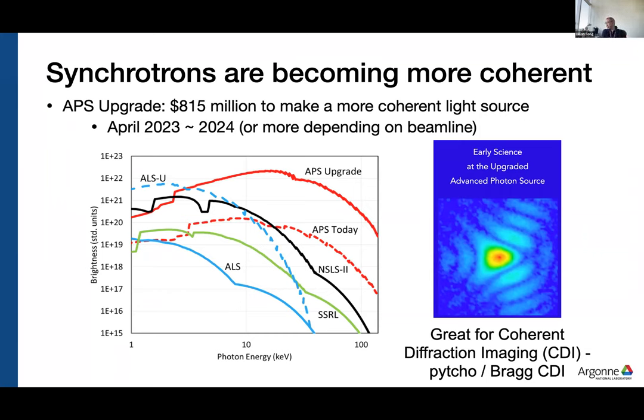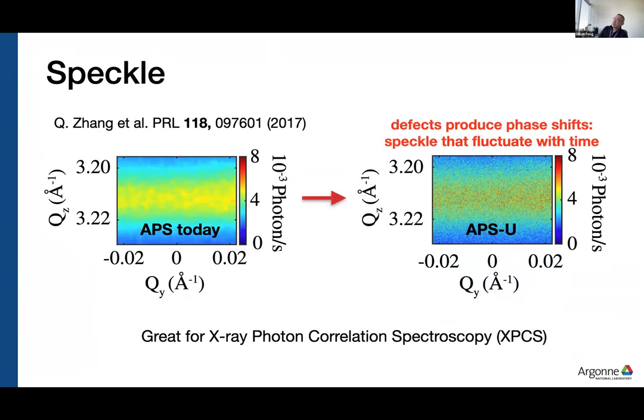And of course, the big winner is CDI or coherent diffraction imaging. People here, of course, like to do ptychography and Bragg CDI, where you look at a Bragg peak, for example, and you look at the scattering on your area detector. And because you're scattering coherently, you could do a 3D volume map of your Bragg peak, and then invert that by a Fourier transform into your nanoparticle, whatever you're looking at. The other big winner that I want to emphasize is XPCS, or X-ray photon correlation spectroscopy.